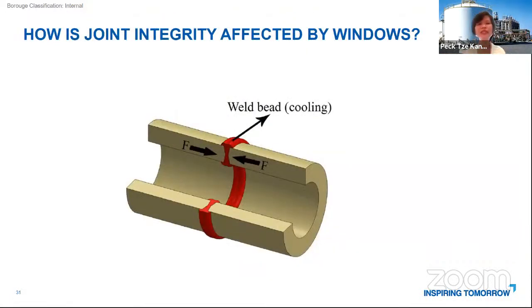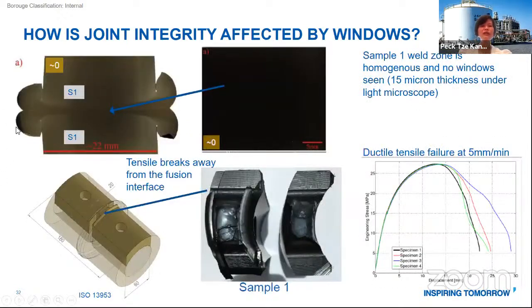So what about the jointing? If we are to join 2 pipes with very poor carbon black dispersion, is there any effect on the joint integrity? So we did this jointing comparison between sample 1 and the other 3 samples. What we did is, first we joined the pipe and then we cut across the joints in a cross section and did a microscopic analysis as well. And we see that it's a very homogeneous weld because the two matrices are quite similar. So the melts are able to flow between the 2 pipes.